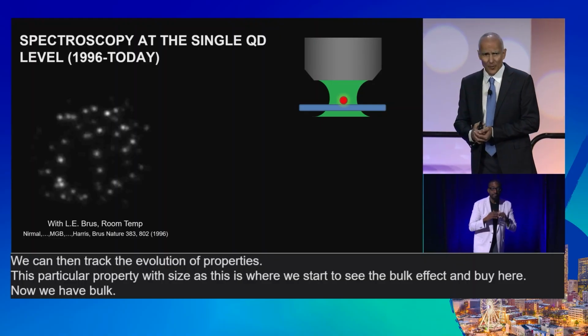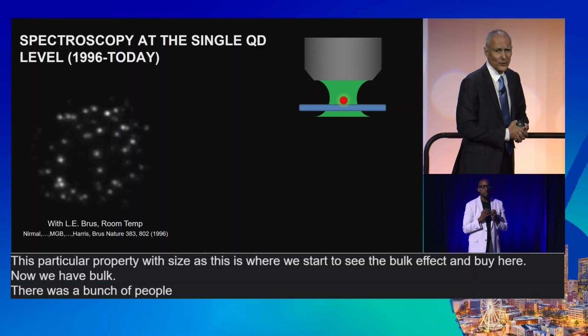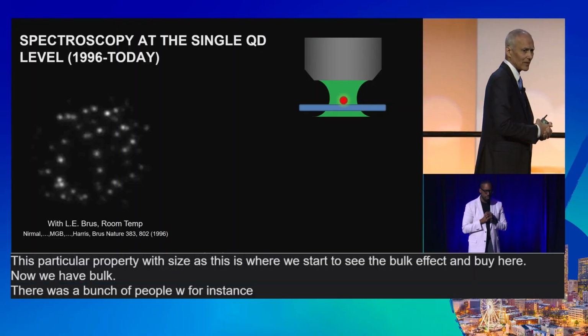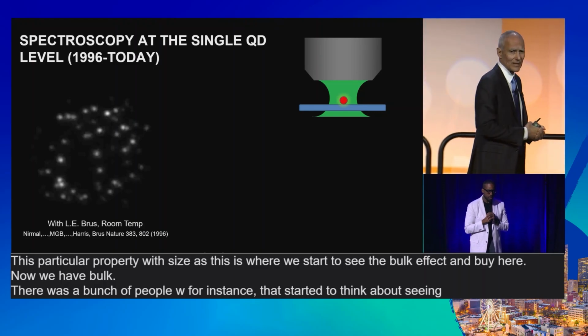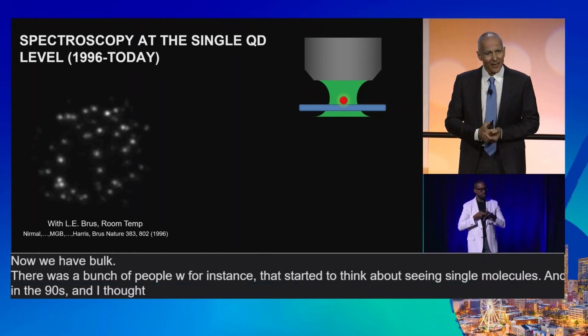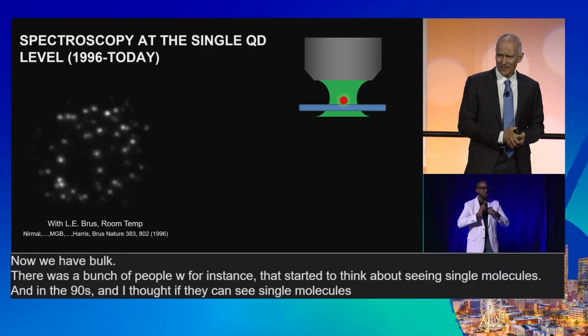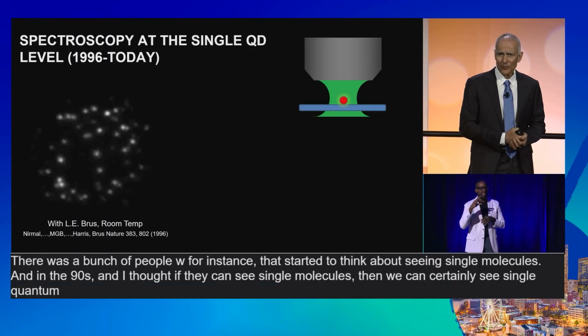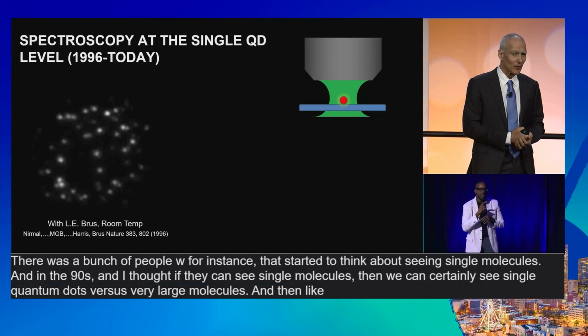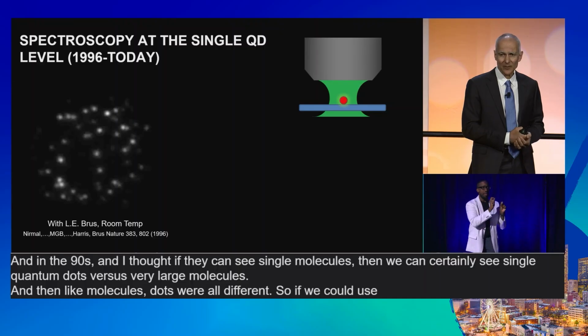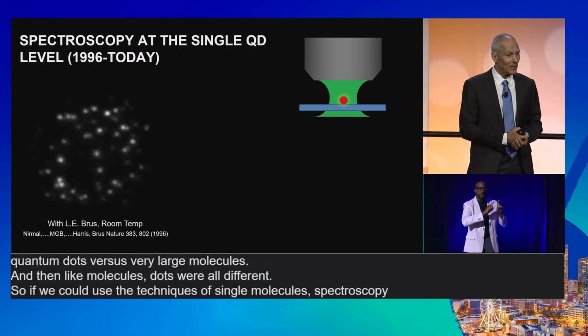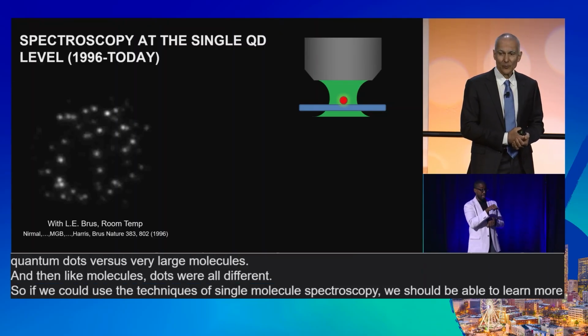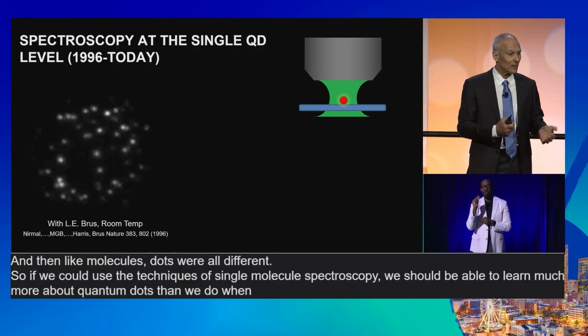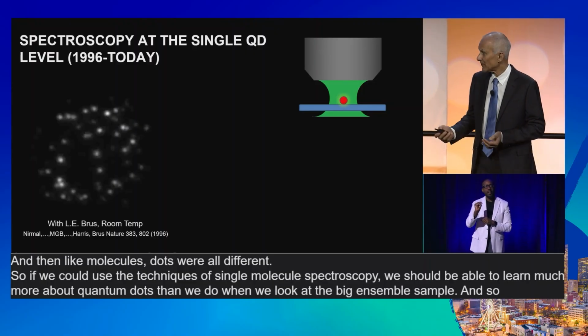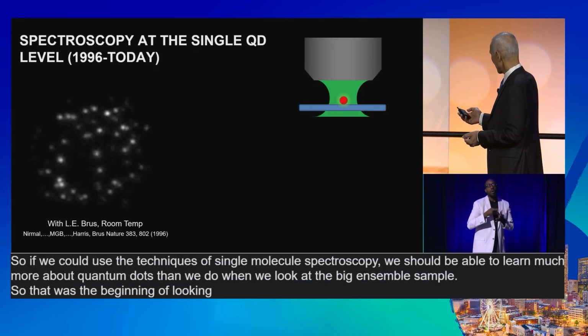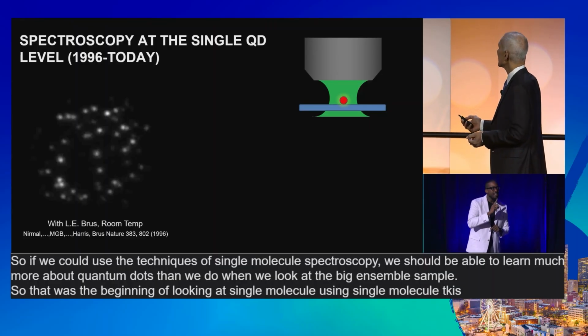There was a bunch of people, W. Moerner, for instance, that started to think about seeing single molecules in the 90s, and I thought, if they can see single molecules, then we can certainly see single quantum dots. They're very large molecules, and like molecules, dots were all different. So if we could use the techniques of single molecule spectroscopy, we should be able to learn much more about quantum dots than we do when we look at an ensemble sample. And so that was the beginning of using single molecule techniques to look at quantum dots.